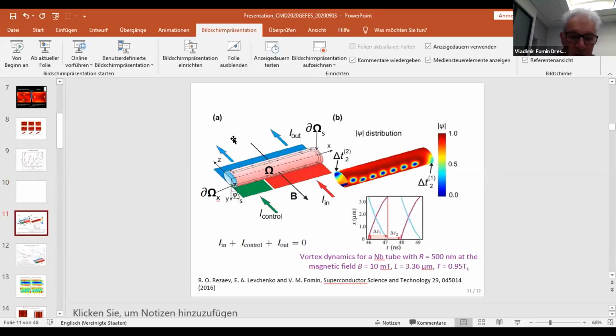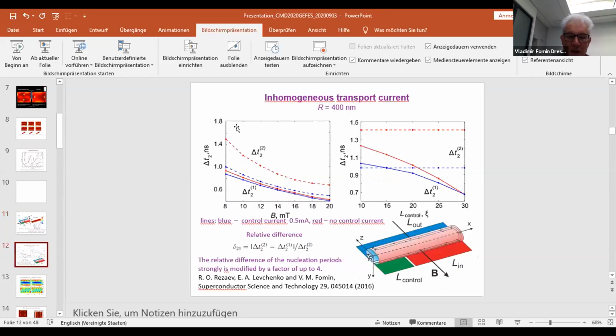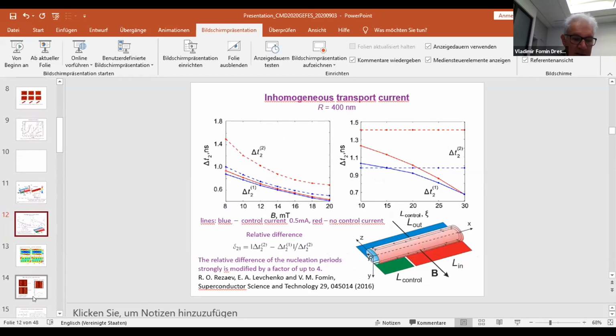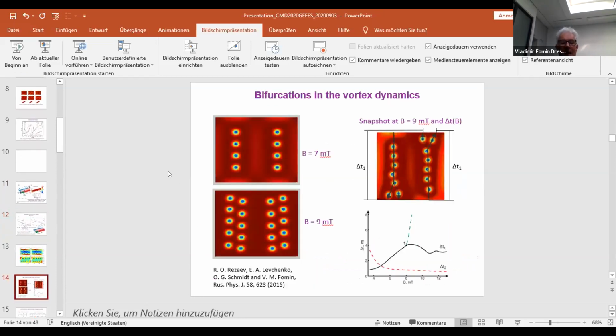But I go now to the next. These properties can be controlled by introducing inhomogeneous transport currents by splitting contacts, which also will influence the characteristic times. What will be if we increase the magnetic field? At a certain magnetic field, there should be a transition from one chain to two chains. And if the transport current is not strong, this takes place via bifurcation, as shown here.